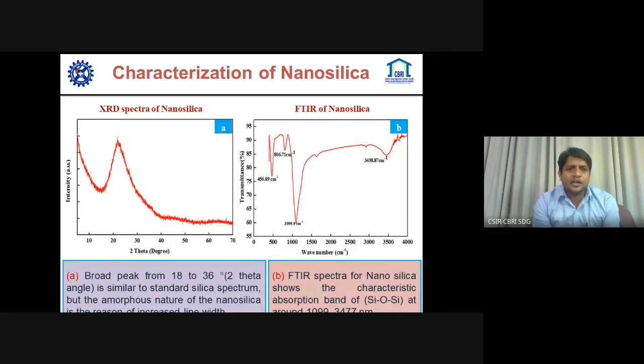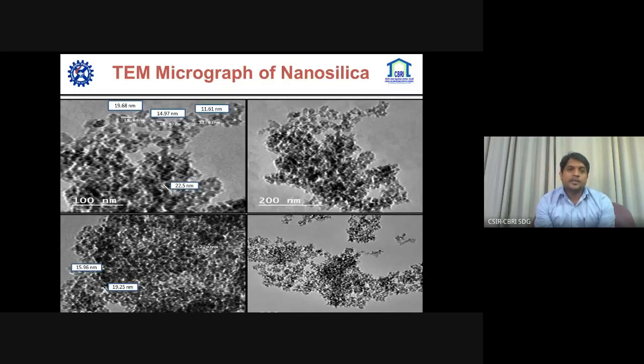In the characterization of this nanosilica, the broad peak in the XRD spectrum from 18 to 36 2-theta angle is similar to the standard silica spectrum, but due to the amorphous nature of the synthesized nanosilica, the width of the peak is increased. That can be seen in the figure. The FTIR spectra of nanosilica shows the characteristic absorption band of Si-O-Si at around 1099 and 3477, which confirms the synthesis of nanosilica from boiler ash. And when we performed the TEM analysis, it was clear that the synthesized nanosilica was spherical and monodispersed, with particle size ranging from almost 10 nanometers to 25 nanometers.